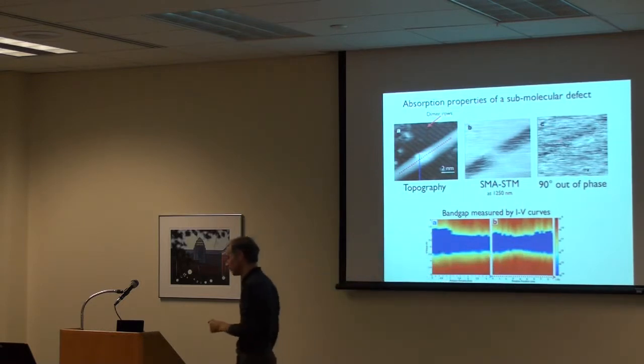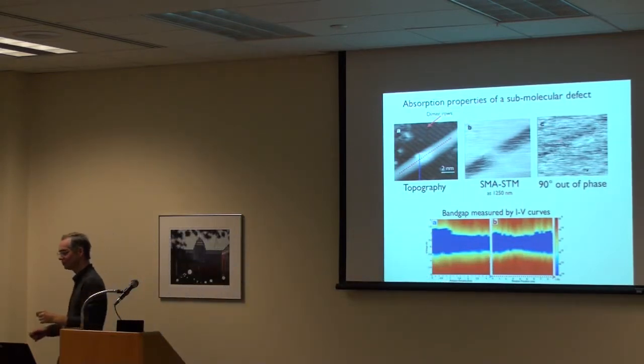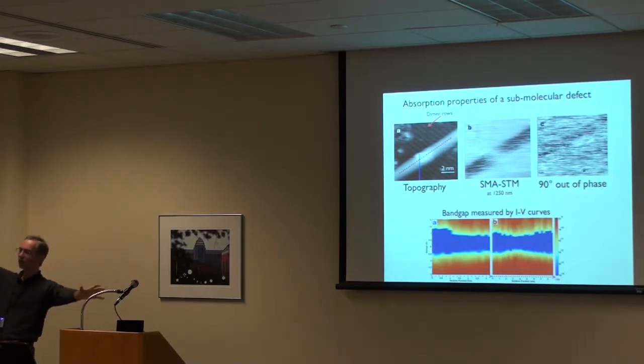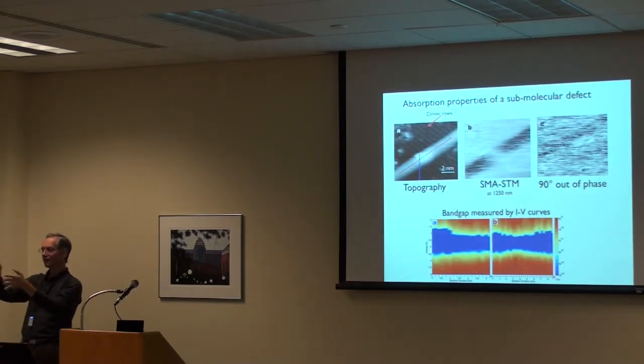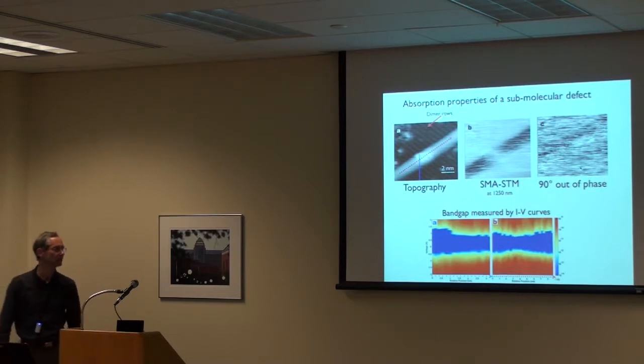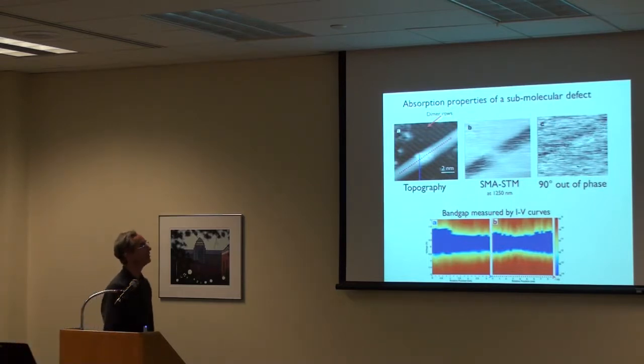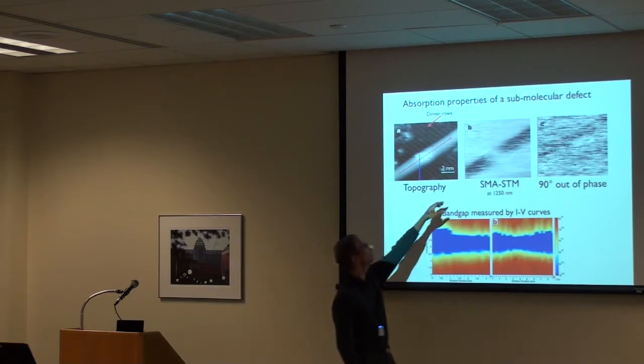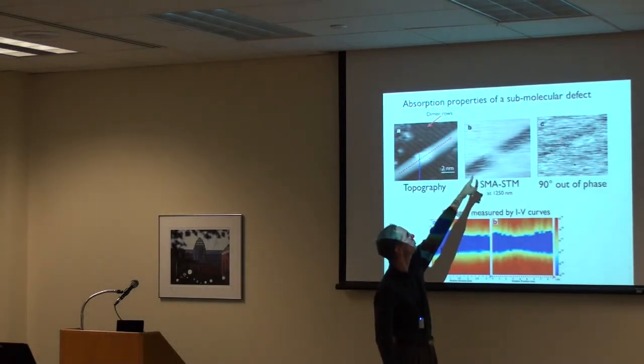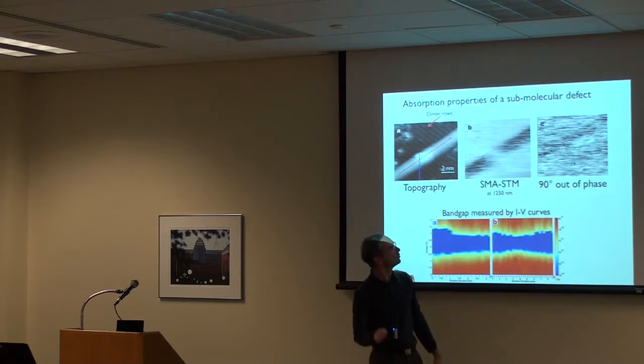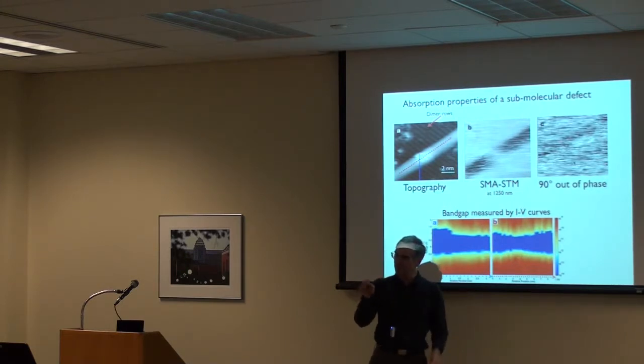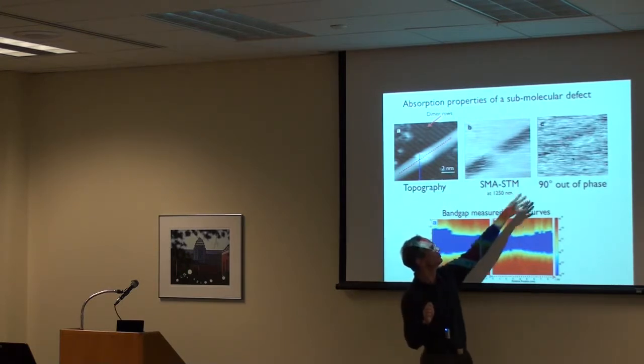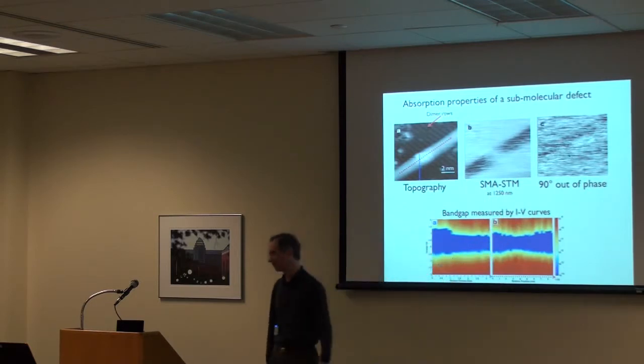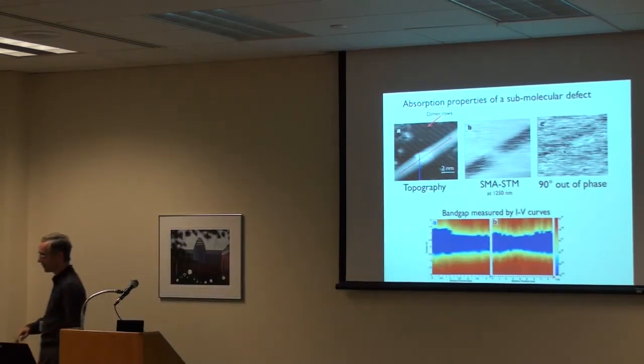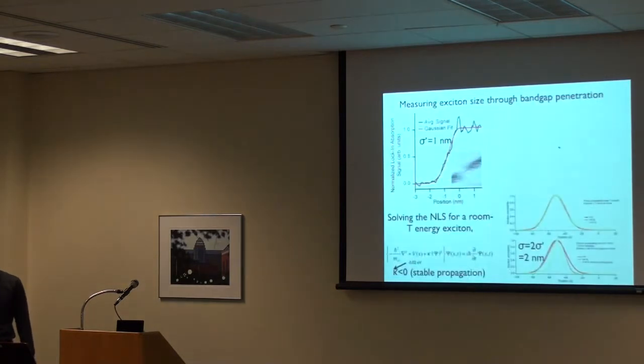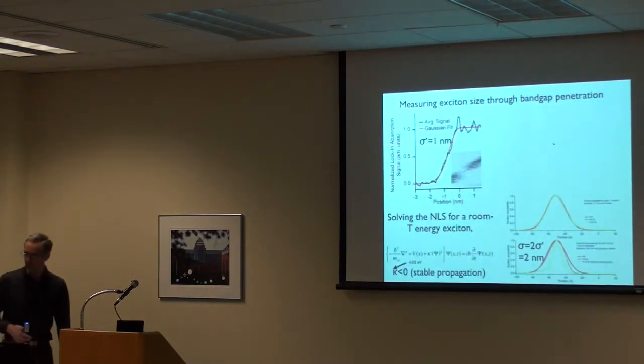What that would suggest is that if we tune the laser into resonance with the nanotube at the top and bottom, you're going to be out of resonance with the middle part, because the band gap has changed quite drastically, by 40% in this case. And that's what you observe here. You get an absorption signal over here and at the top, and you don't see anything in the middle. Because we're using phase-sensitive detection, and I mentioned that we're modulating the laser, we can also go to 90 degrees where you don't expect to see a signal, and we mostly just see noise there. So there's an optical measurement that works together with the current measurement.